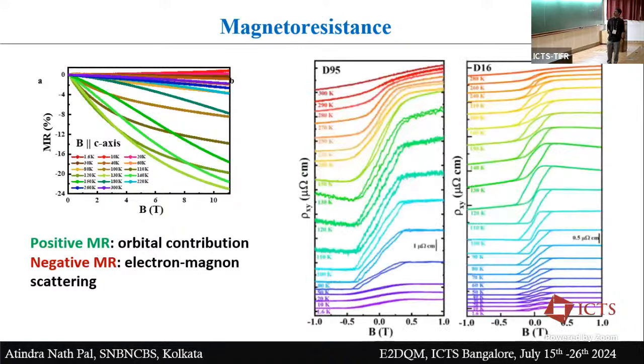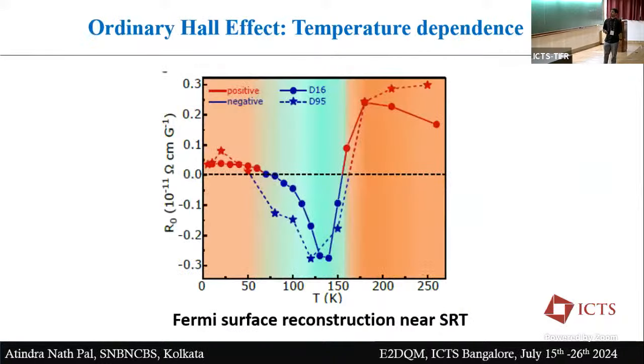Okay. So also Dhawala was asking about the hysteresis. You can see in the 95 nanometer thick layer, we also observe this hysteresis, and if you go to the thinner layer, it becomes more hard magnet type hysteresis. Okay, so now I'll come to the very interesting result of the Hall data.